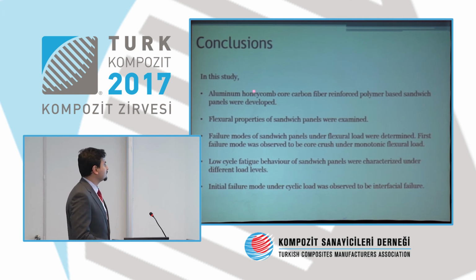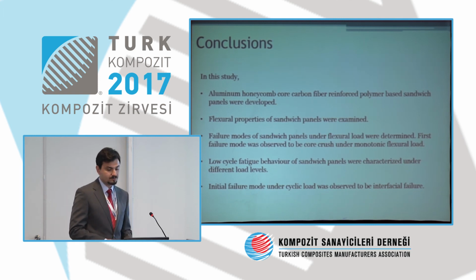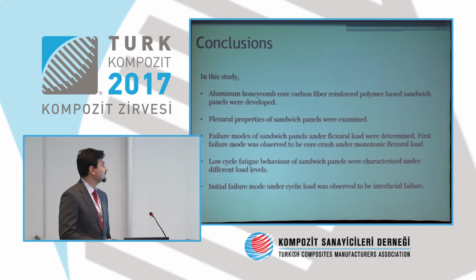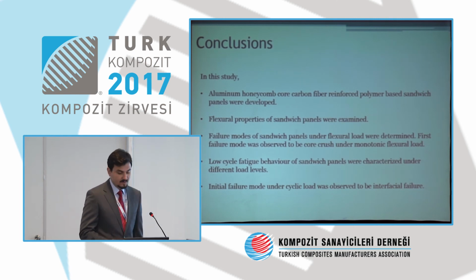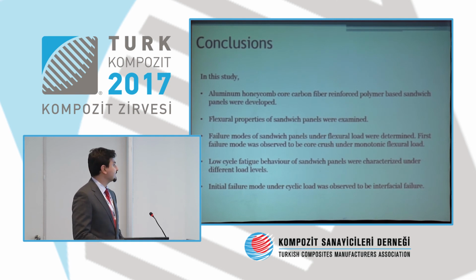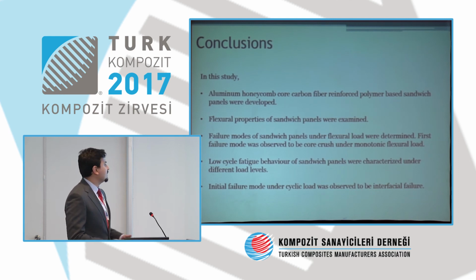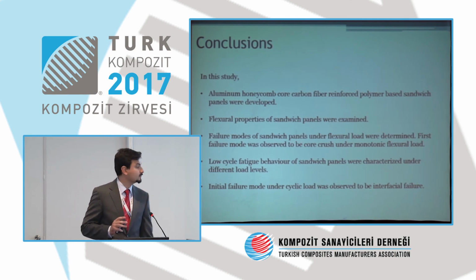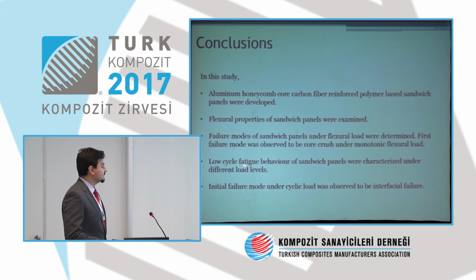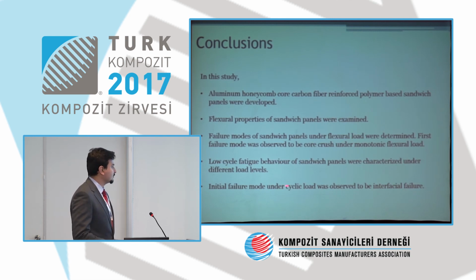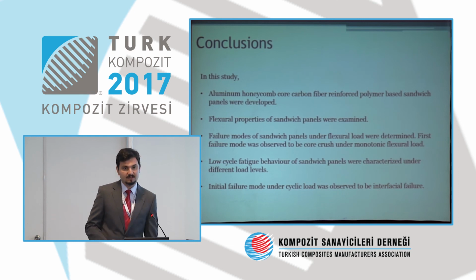Okay, to conclude, in this study, aluminum honeycomb core, carbon fiber reinforced polymer-based sandwich panels were developed. Flexural properties of sandwich panels were examined. Then the failure modes of sandwich panels under flexural load were determined. First failure mode was observed to be a core crush under monotonic flexural loads. Low cycle fatigue behavior of sandwich panels was characterized under different load levels. And the initial failure mode under cyclic load was observed to be interface failure.